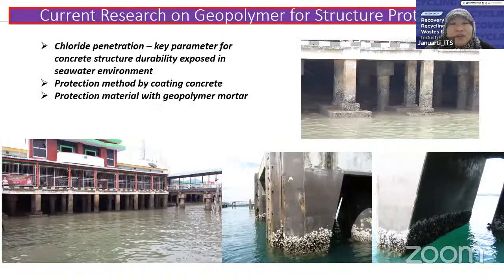And this is one of the pictures we took from Tanjung Balai Karimun, one of the islands very near to Riau Island. We can see here that these piles have a lot of corrosions. We can also see a lot of barnacles. We call it biofouling. It's a very common phenomenon on the beach and also in the coastline. And corrosion will occur not only because of the chloride ion, but also the attack of the barnacles. So what should we do with this structure?